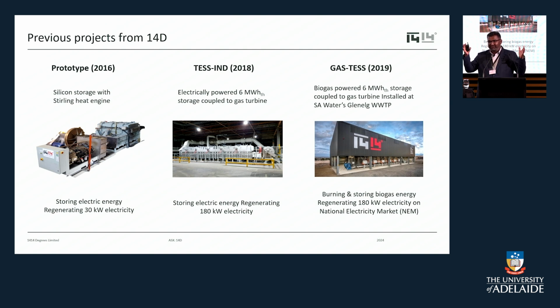And that's why these regenerators, with a very, very high delta T across the flame temperature and the bricks, you can heat them up very fast. So in these thermal energy storage systems, the challenge is not just recovering the heat from them, it's also putting the heat into them in the fastest way possible, right? So we realized all of these and looked at these boxes. What came to the front was the scalability of these boxes is quite poor. Secondly, when you're trying to couple an electrical energy source at 1400 degrees Celsius, then you need to be able to absorb this heat as quickly as possible into the storage media, which brings in the thermal conductivity aspect. It is quite understated how important thermal conductivity can be for thermal energy storage systems, right?